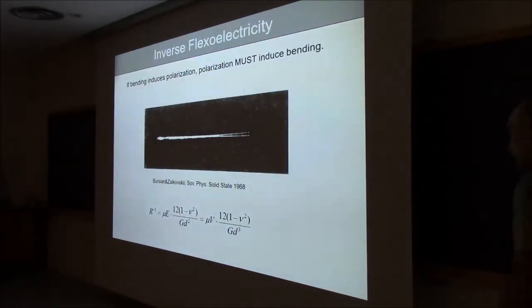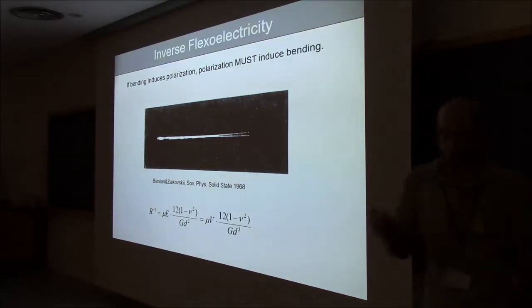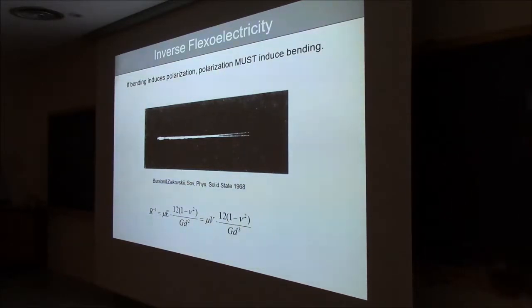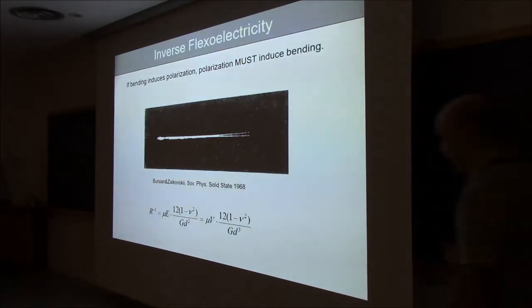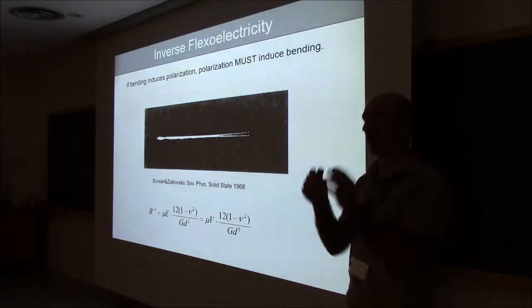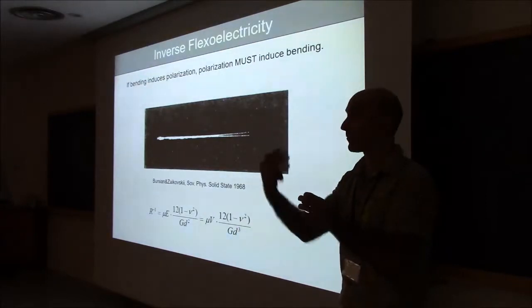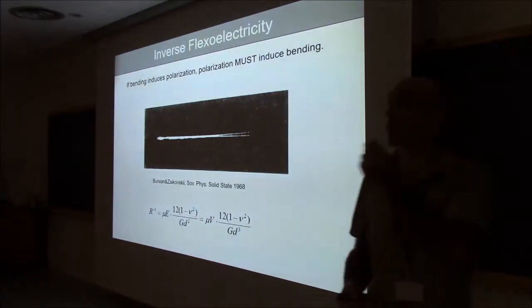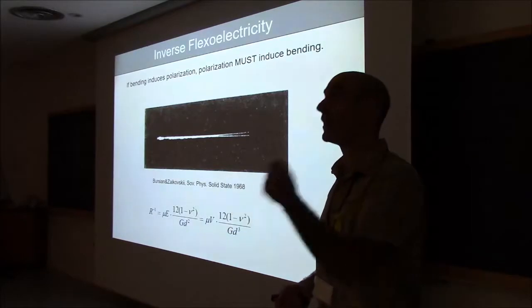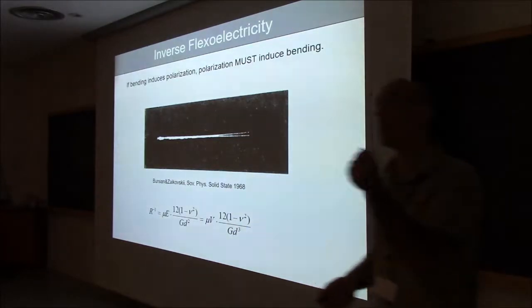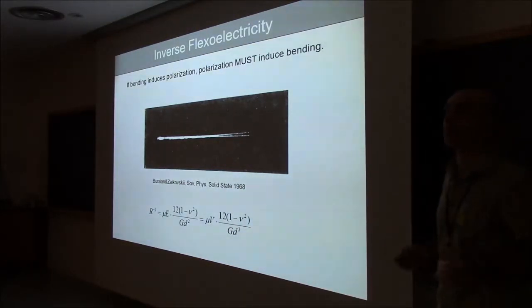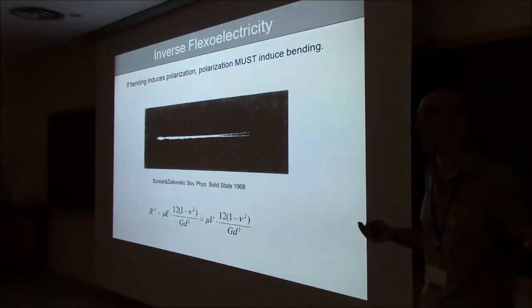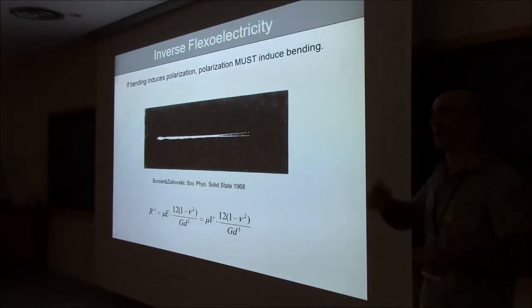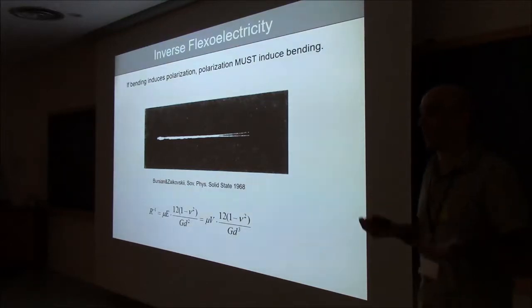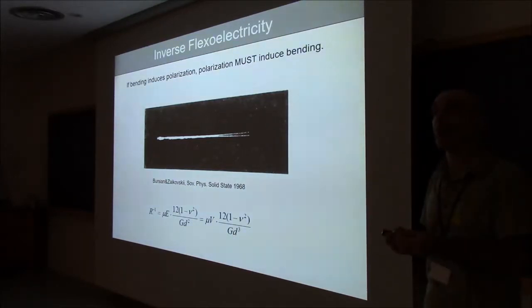Okay. So I just mentioned, unlike electrostriction, piezoelectricity and flexoelectricity do have the inverse effect. So in the same way that if I bend something, it will give me a polarization, if I try to polarize something, if I apply voltage to something, it will try to bend. Now how much it manages to bend will depend completely on the thickness of your sample. If you have a very thick slab and you apply a voltage, it will try to bend, but it won't manage. But if it's sufficiently thin, it will bend.